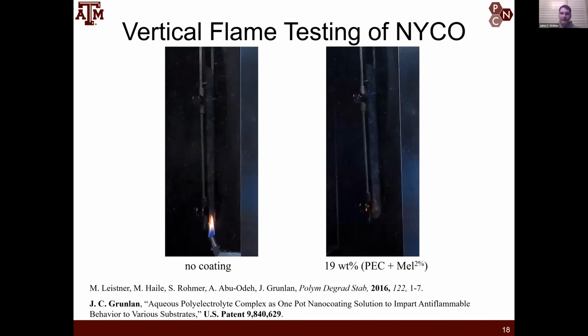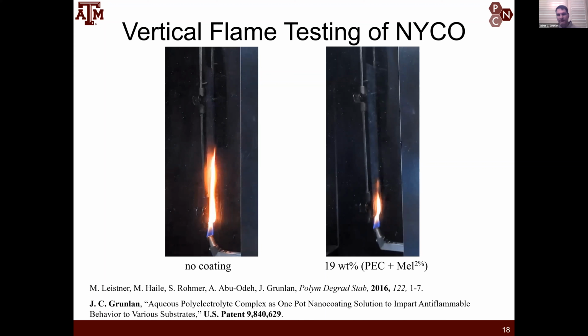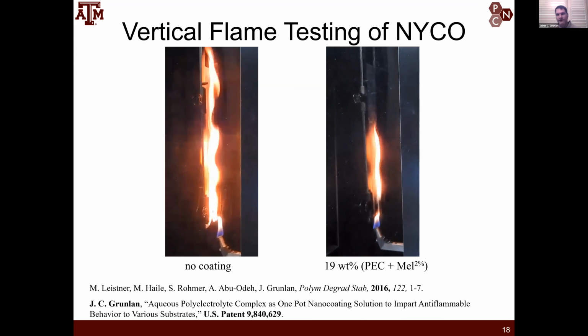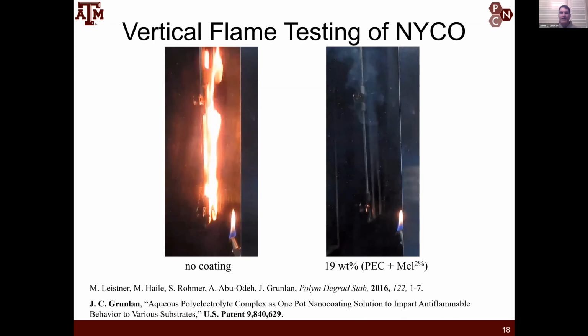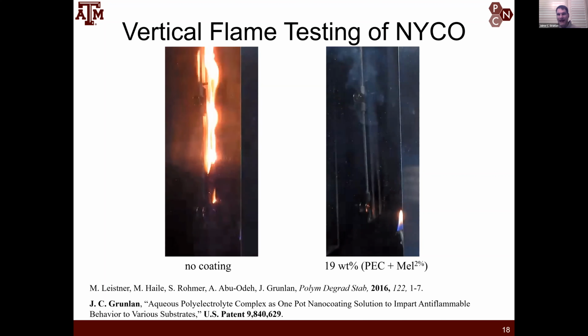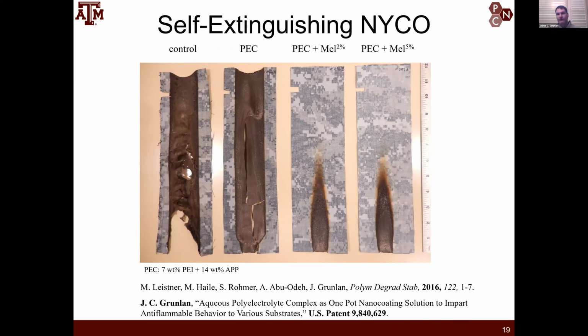And then now if we look at the vertical burn of nylon cotton, if there's no coating, you're going to see that in this video, it's burning much more vigorously than the cotton was burning. You can see how bright that fire is and how aggressive it is. But in the complexed coating that has the melamine, you can see it added 19 weight percent. The coating added 19 weight percent to the textile, but it created this self-extinguishing effect, and it passed the ASTM D6413 vertical flame test. And so we looked at different melamine concentrations, and it turned out above a 2% in water melamine solution, there was no need to go higher in concentration.